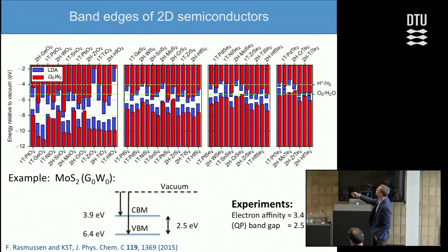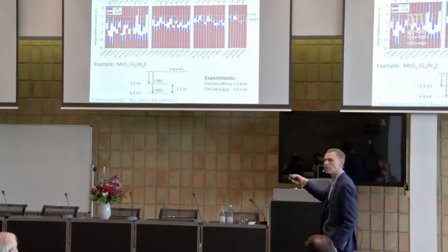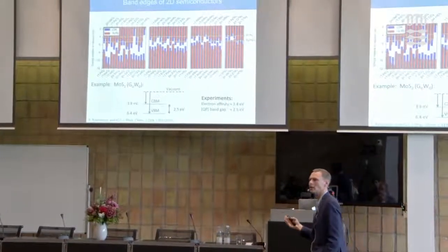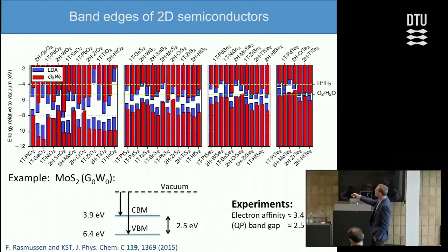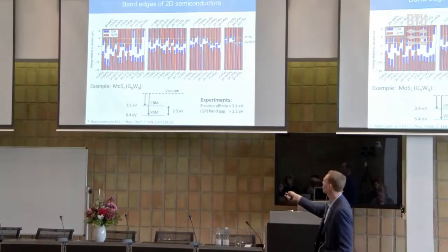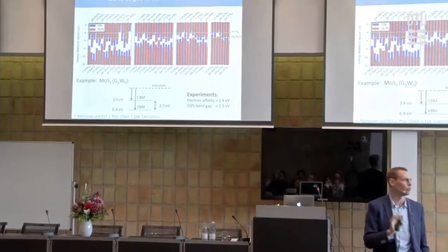There are two types of calculations here. The red bars are the GW method we're using, and the blue is a more standard single particle approximation called LDA. If we take the GW result and compare the conduction band minimum and valence band maximum to experiments, the gap is calculated to 2.5, in very good agreement with experiments. So on the band gap, we're in very good shape—we can really predict those very accurately.